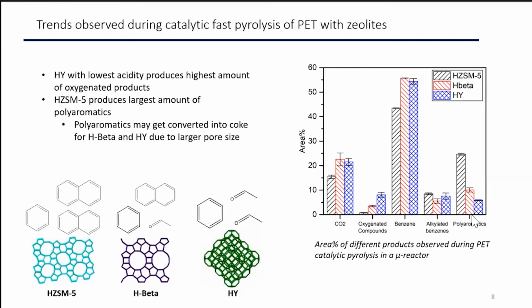So then if we look at the main products for PET pyrolysis, we see that benzene is largely the major product. And we see the effect of the catalyst on these oxygenated compounds: HY, which has the lowest acidity of all of our catalysts, results in the highest oxygenated compounds, and HZSM-5, with the highest acidity, results in the lowest amount of these oxygenated compounds.